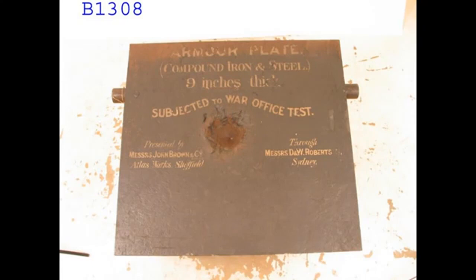The iron also spread the shockwave through the whole plate, the same way that the wood did for the iron, and kept any broken steel elements together in one location, which assisted in resisting follow-up shots. This overall gave armour an instant kinetic resistance bonus of about 20 to 30%, depending on the technique, the material quality being used, and the relative thickness of the two plates that were being sandwiched together.